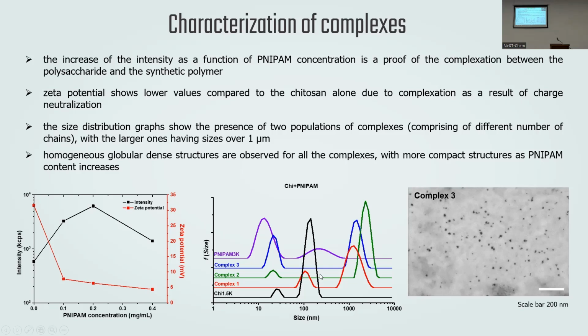From figure 2, we can see the size distribution graphs that show the presence of two populations of complexes comprising different numbers of chains. And we can see that the larger populations have sizes over 1 micrometer. Also from STEM, we observed that homogeneous globular dense structures were formed for all the complexes, but with more compact structures as we increase the PNIPAM content.